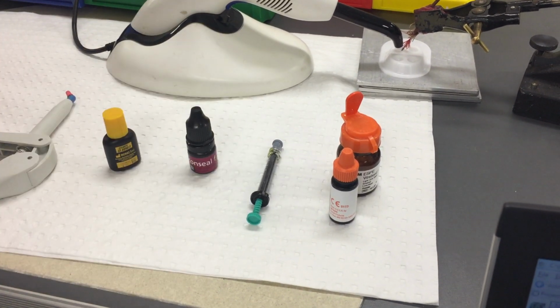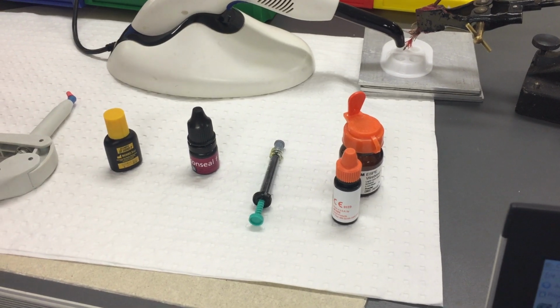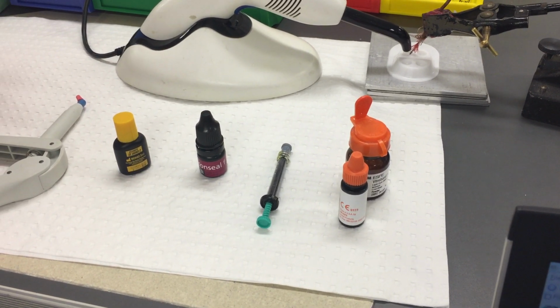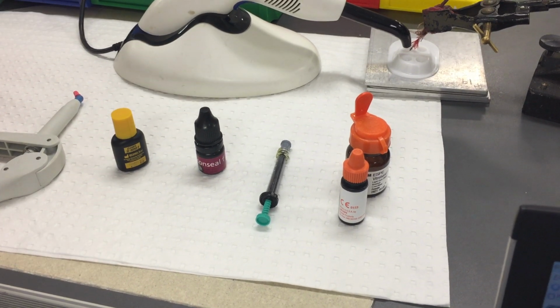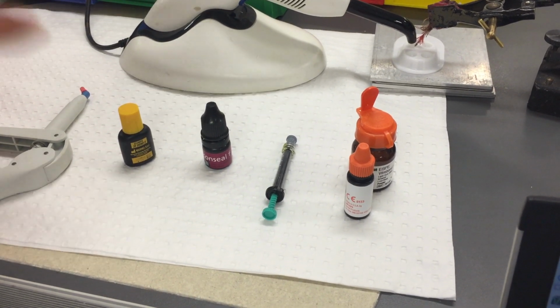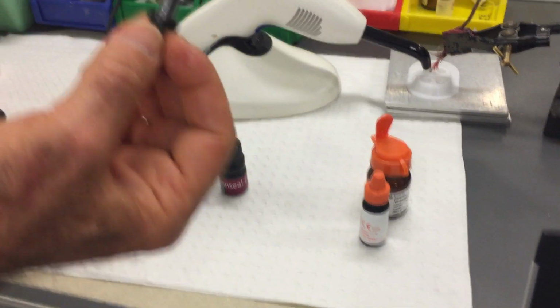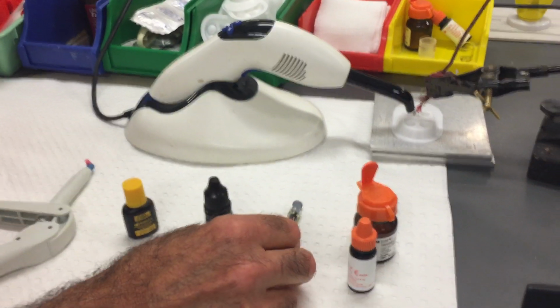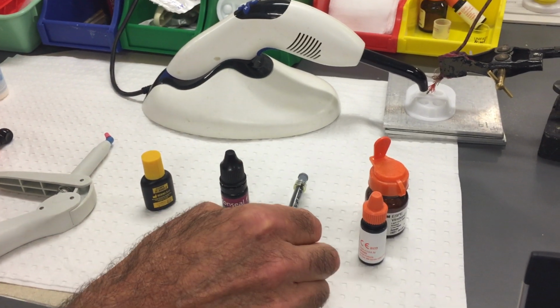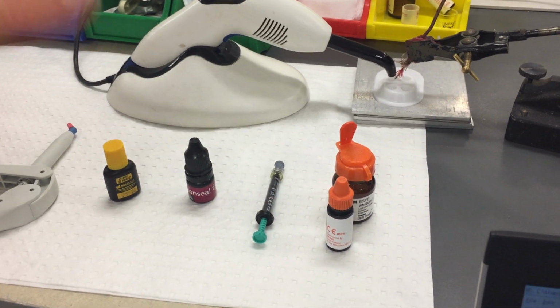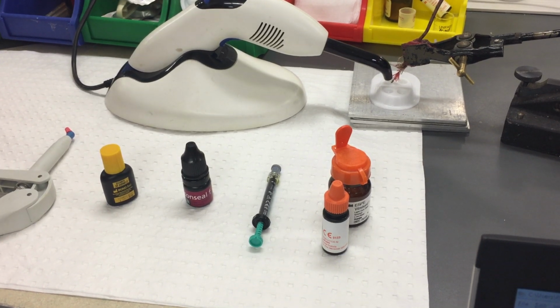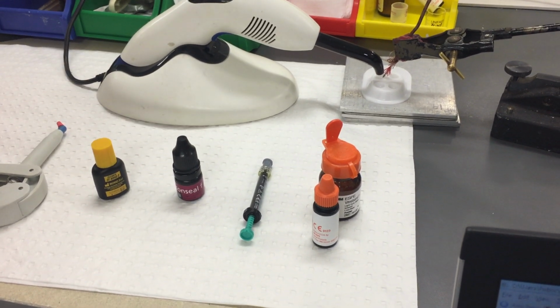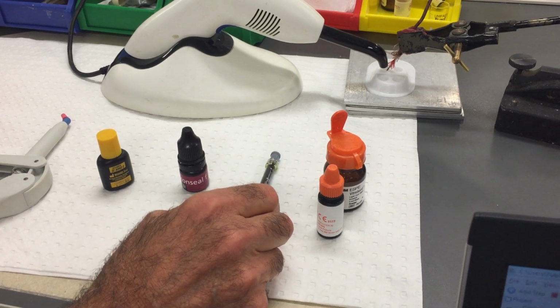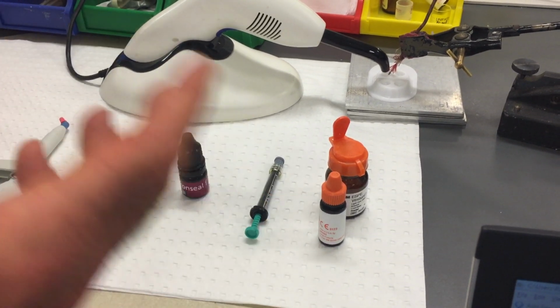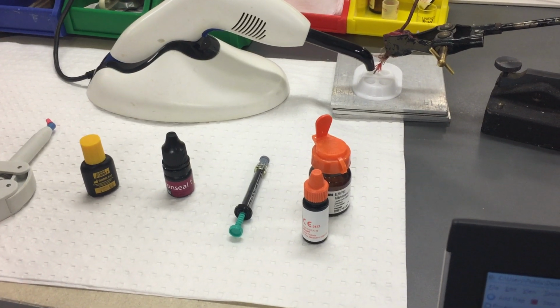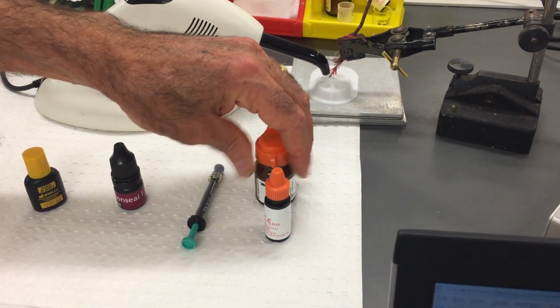So the way you do that is etch that little white fleck with literally very strong acid, hydrochloric acid in fact. You then wash that off, use an alcohol to dry it, and then you infiltrate it with this Icon infiltrant. This has got the same refractive index as enamel, hence the little white fleck disappears, and it also seals all the cavity. Unfortunately, it's not radiopaque, so you need to document its usage, otherwise you will not pick it up on a radiograph. And the last one, as I said, is a glass ionomer cement.